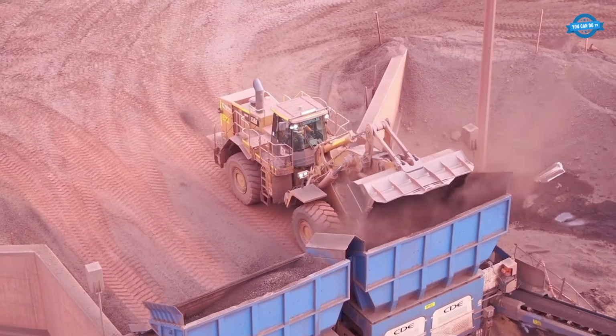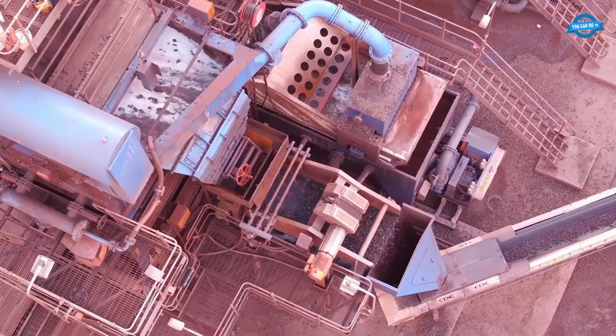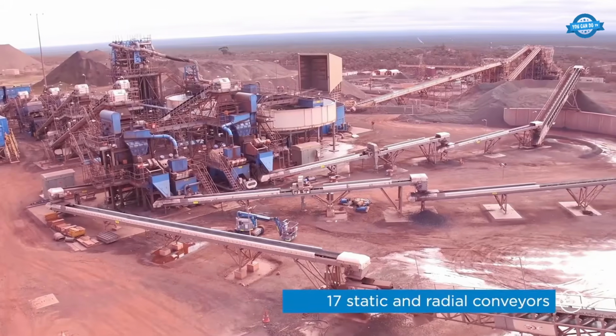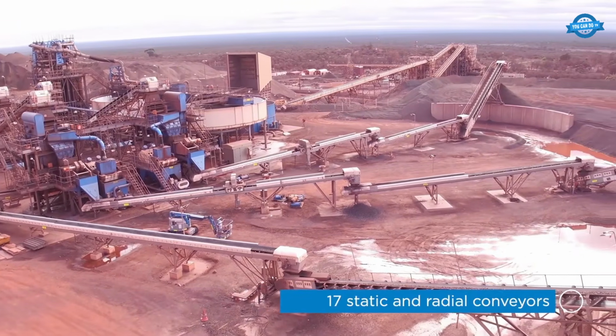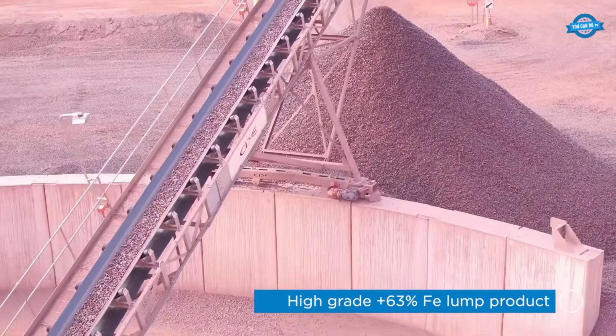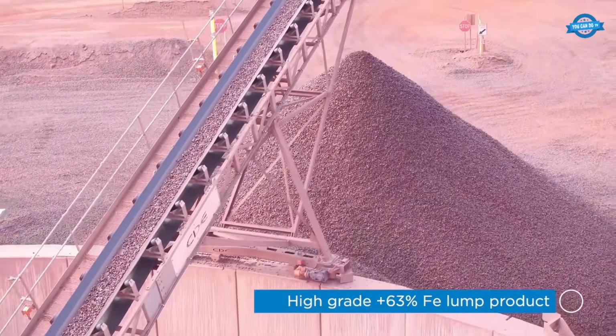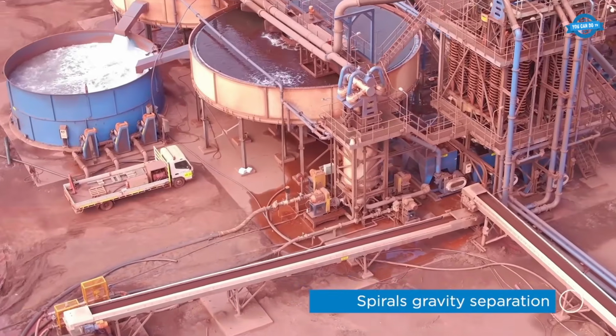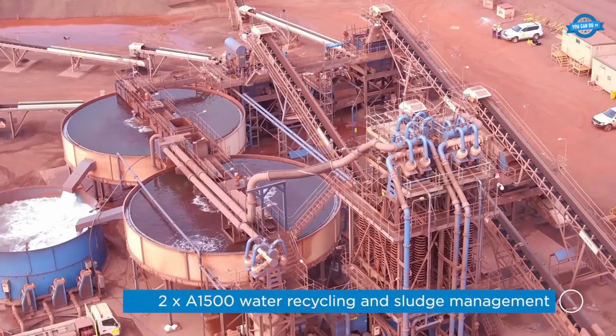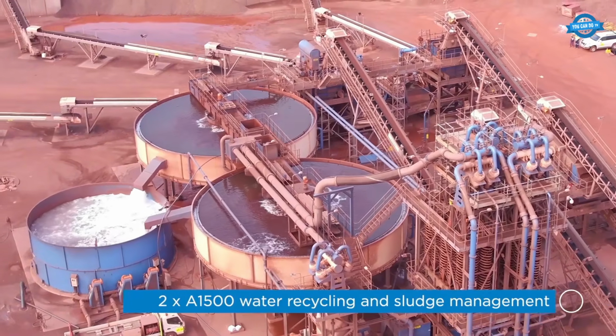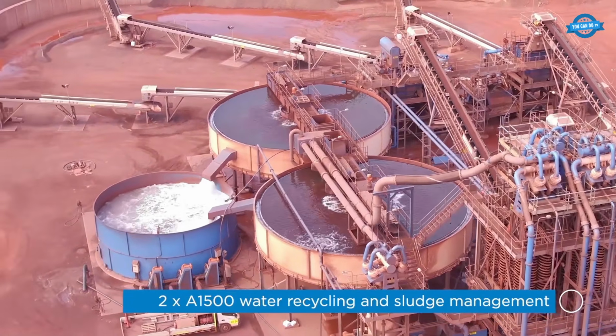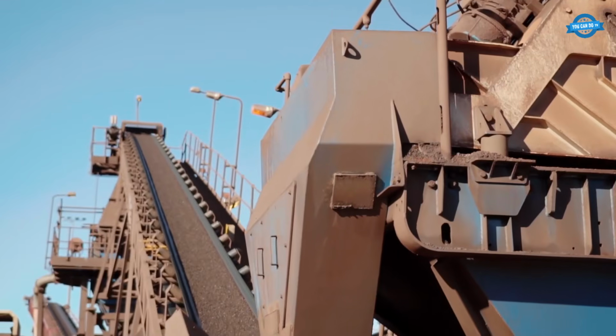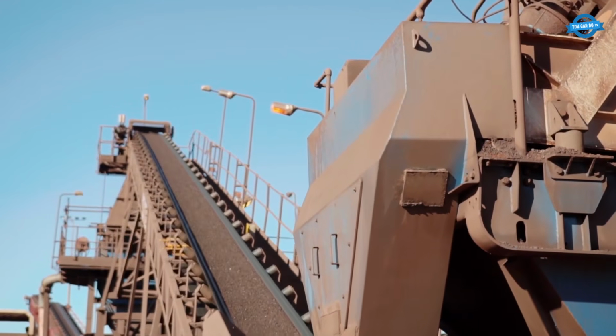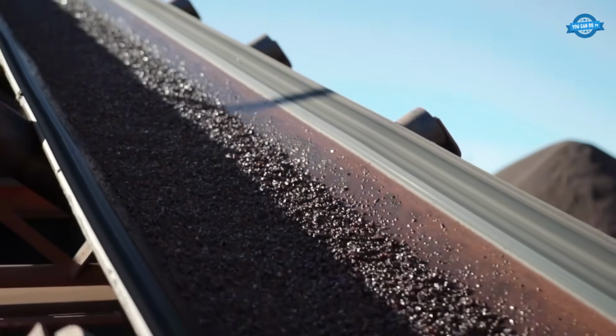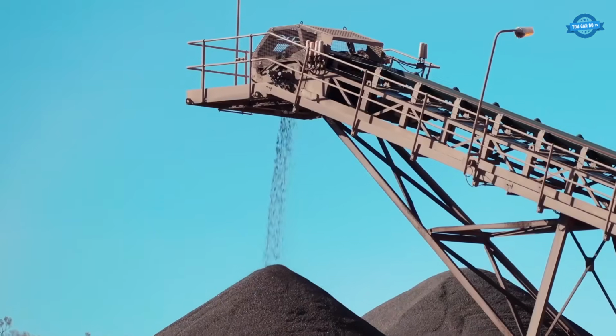Front-end loaders feed raw material in. Scrubbing units break clay off the ore. Jig gravity separators split heavy iron-rich particles from lighter waste. Spirals do a second pass on the finer material. Water gets recycled through the plant, and the finished product stockpiles cleanly on the outbound conveyor. The feed lands at 43 to 52% iron. The output, over 60%. A waste pile just quietly became premium-grade concentrate.